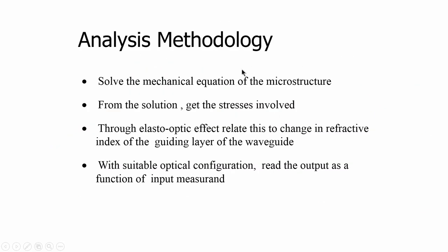So, if you want to study such optical MEMS devices, guided wave optical MEMS devices, we have to deal with the mechanical equations, the optical equations, and if there are any electrical effects, electrical equations, all combined into a single unit. So, first you solve the mechanical equations of the diaphragm, then from the solution you get the stress variations induced, as we have seen in the case of the acousto-optic effect. In this particular case we are using what is called the elasto-optic effect, and you get the stresses involved. Then you can relate these elasto-optic effects to the refractive index variations of the waveguide, and you can choose a proper optical configuration like the Mach-Zehnder interferometer. In that particular case, read the output as a function of input signals. This is the broad methodology.